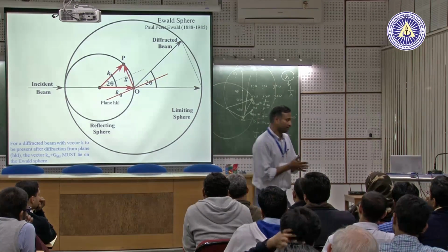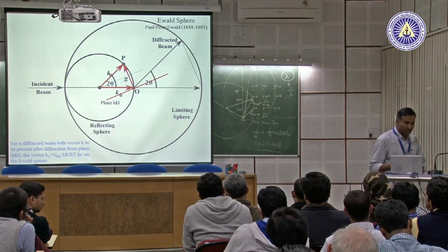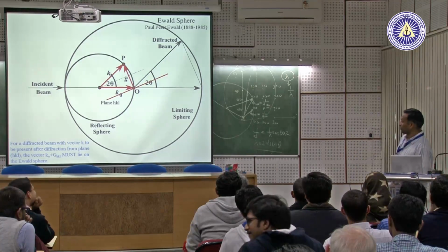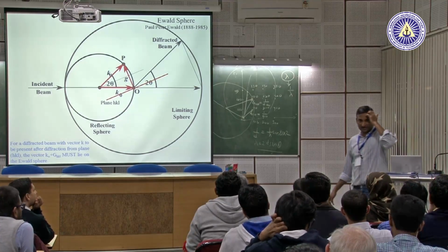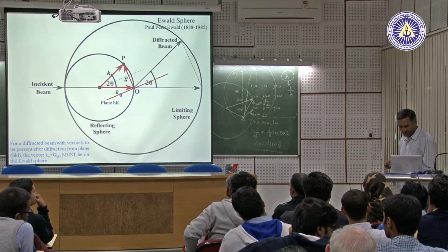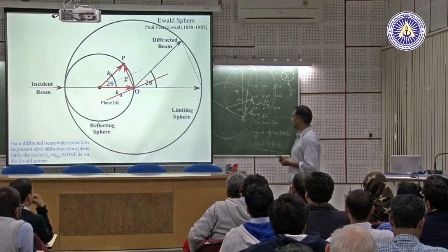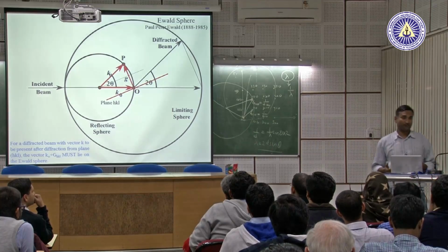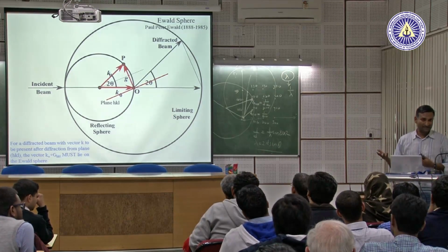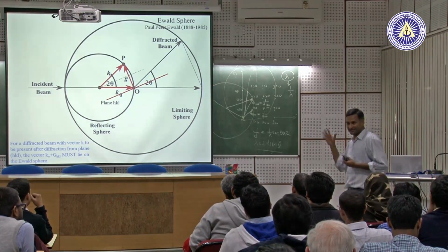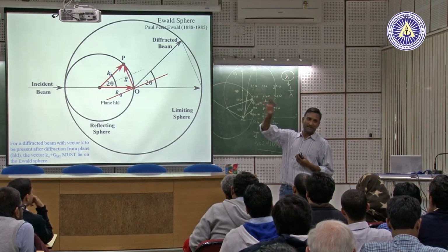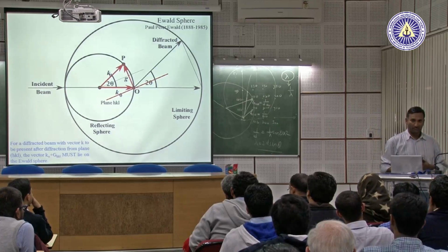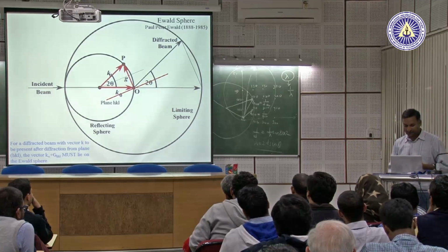But traditionally, what was done was to choose white radiation, a radiation consisting of many wavelengths. So instead of rotating the sample or the beam to collect multiple points, you can choose wavelengths of different magnitudes in the same beam and create many more Ewald spheres which will intersect with many more points, giving you many more diffraction data.